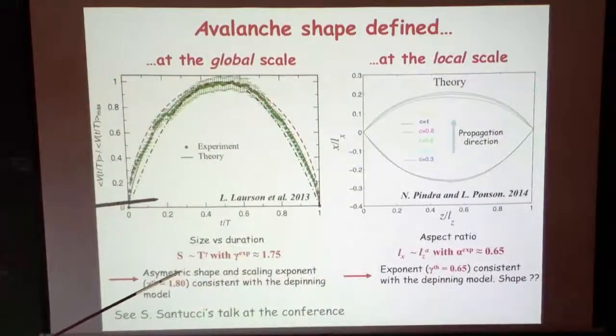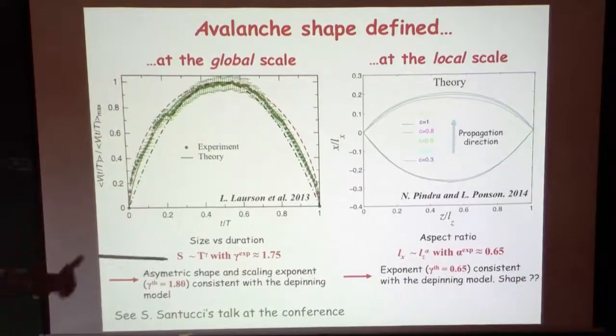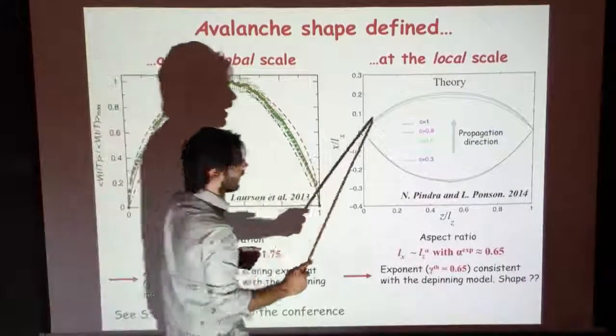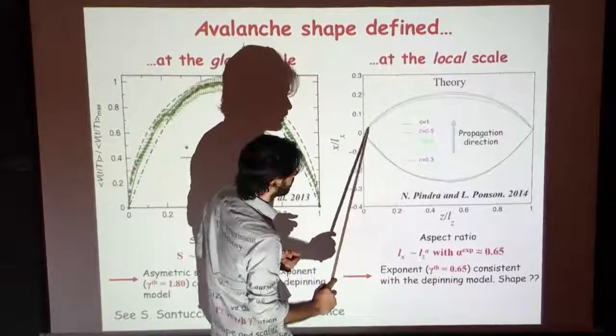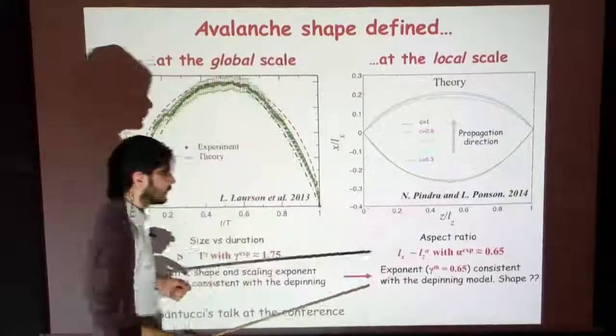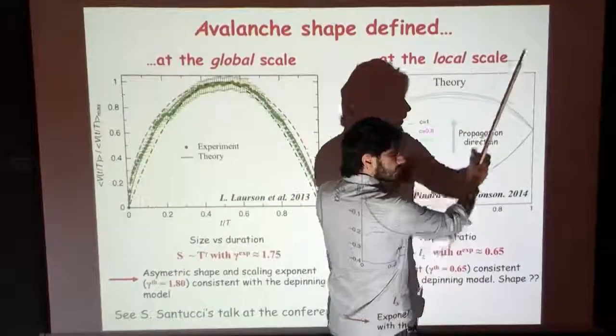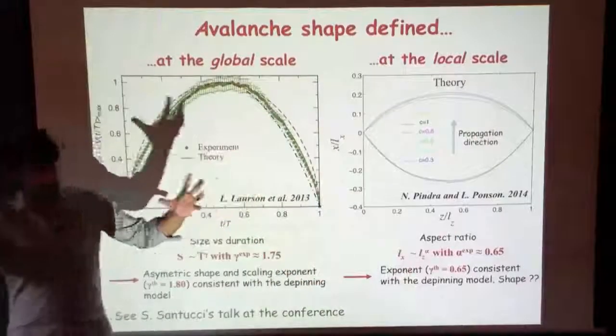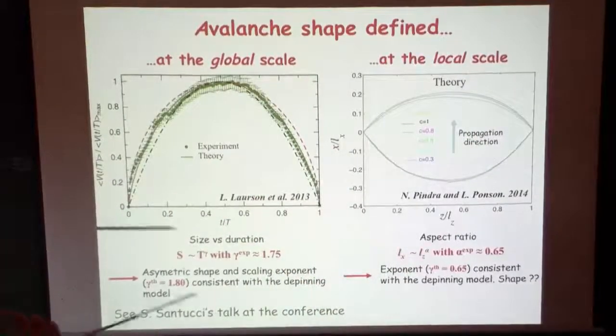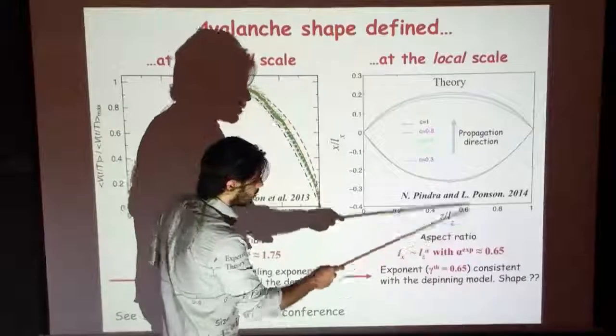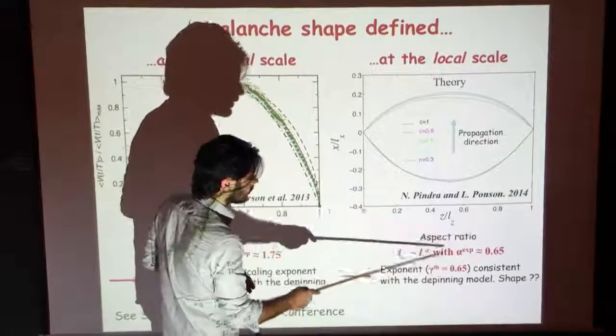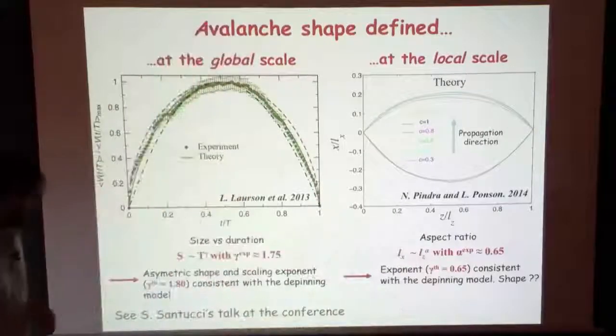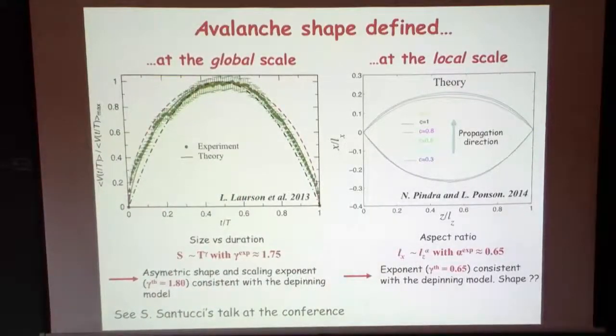Using numerics, resolving the equation of evolution numerically, you also see that the average shape of the cluster is asymmetric. This is the propagation direction, so it's more extended backward than forward. So you have a kind of feeling of how this avalanche can develop. They can start here, propagate spatially, and close up this way. The shape has not been compared with experiment, but the aspect ratio follows a scaling law that compares well with the experiment.